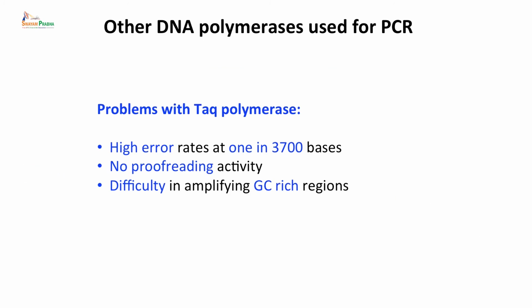Now, the problem with the Taq polymerase is that, first of all, when it is doing the polymerase reaction, it introduces errors, and it can introduce up to 1 error in 3700 bases. So if you have a long template, say supposing you have a 5 kb template or 6 kb template, then the Taq polymerase can introduce several errors. Because it has no proofreading activity, you remember that DNA polymerases also have 3' to 5' exonuclease activity, and so this enzyme lacks this proofreading activity, so it cannot correct if it has incorporated a wrong base.